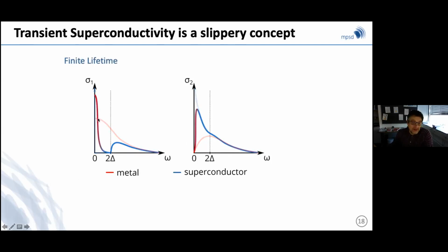And for a lifetime that is some sizable fraction of the gap, what I'm left with is a high mobility metal, which is effectively a scattering rate, which is the lifetime of the state. And so at some level, one wouldn't go as far as saying that this is a pseudo assignment, but one needs to be very careful when one characterizes these features, only looking at frequency scales that are significantly larger than the inverse lifetime of the state, so that one is really talking about quasi-static features. Not quasi-static in the sense that the system is not thermalized, which would be at least a subtle issue, but just in the way the measurement is made, I can only trust data at frequencies higher than the inverse lifetime. I mean, this is somewhat an obvious statement.